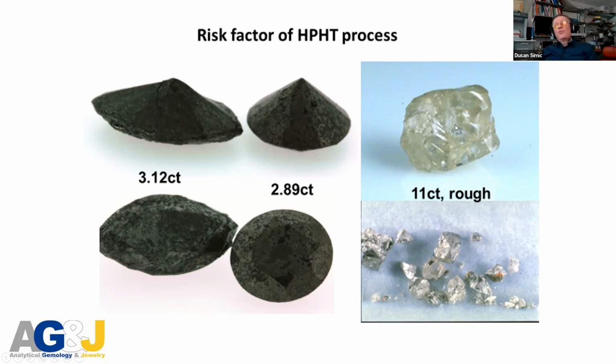When we tried to anneal this rough that Branko brought, from Russia I think, okay, doesn't matter, finally the color became very high, but you see what is left of it. We never did rough stone again, especially of this configuration, so heavily with so many structural defects inside.